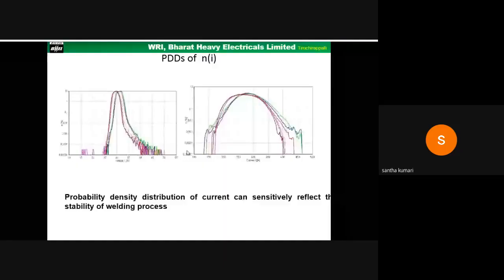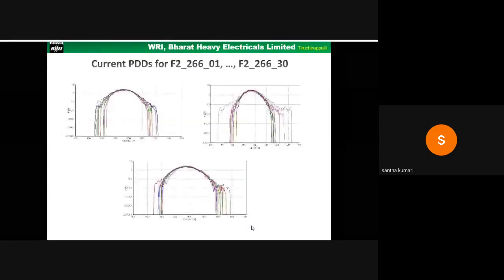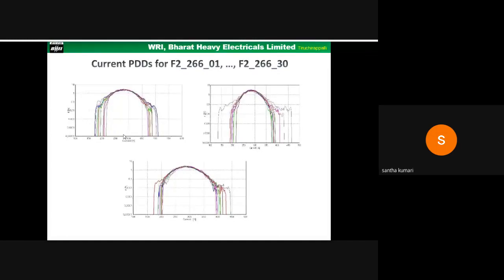Since the current waveform sensitively reflects the stability of the welding process, we divided this 30-second data into 1-second data. 30 sectional curves of PDDs were obtained, and since there were higher fluctuations in the current PDDs, this confirmed that there was a higher inhomogeneous flux or mineral distribution. The intersections of these sectional curves with the axis are less uniform, corresponding to the Imax and Imin. In this way, we were able to analyze the flux filling of the flux core wire. In this way, we can use this digital electronic data acquisition system for analyzing welding consumables.